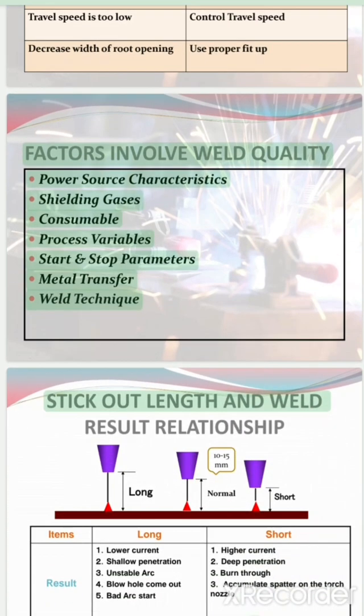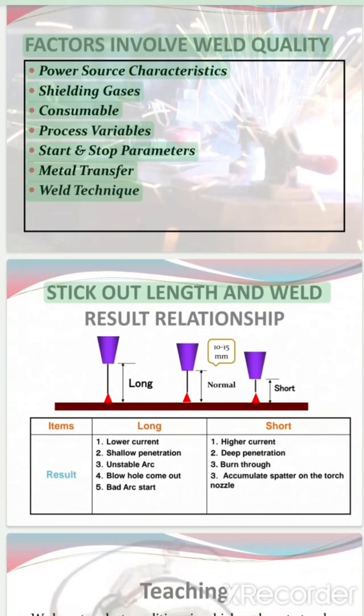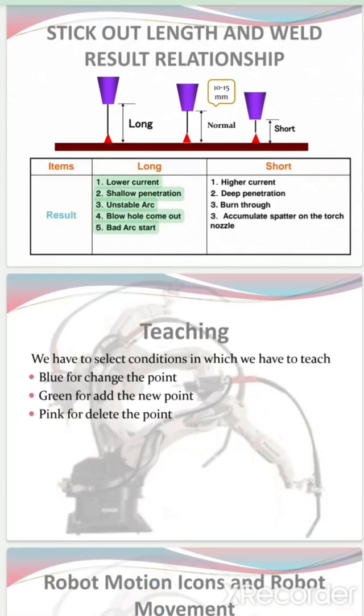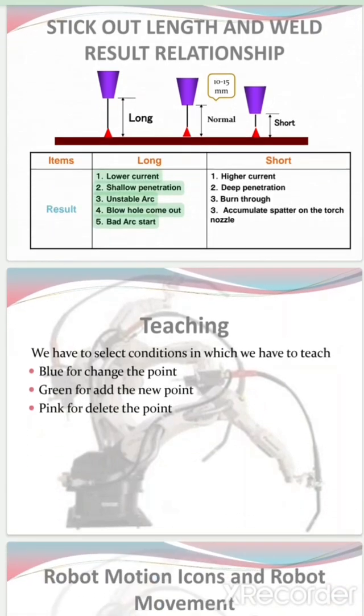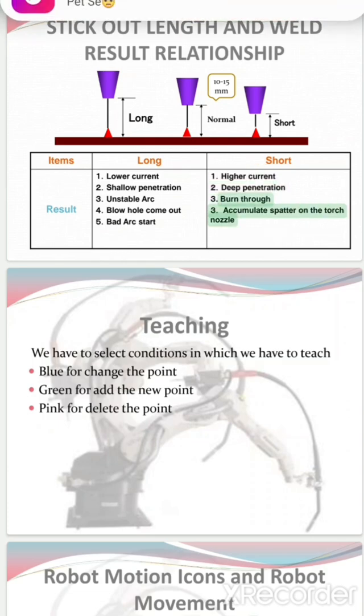Factors involved in weld quality: power source characteristics, shielding gases, consumable process variables, start and stop parameters, metal transfer, weld technique. Stick out length and weld result relationship. Items: long, short. Result: long stick out gives 1. lower current, 2. shallow penetration, 3. unstable arc, 4. blowholes come out, 5. bad arc start. Short stick out gives 1. higher current, 2. deep penetration, 3. burn through, 4. spatter accumulates on the torch nozzle.